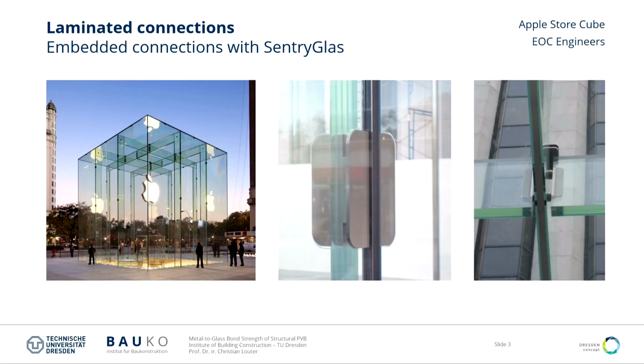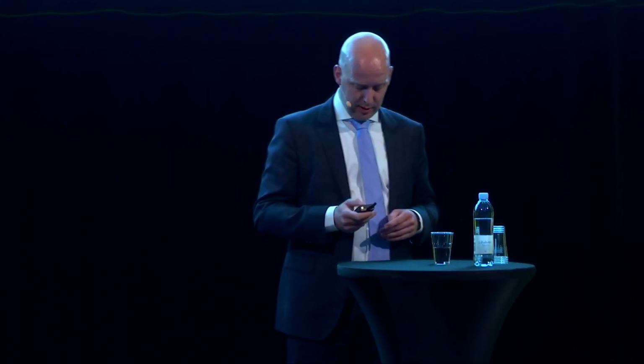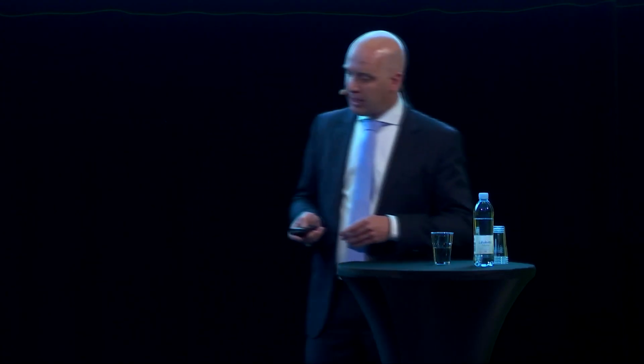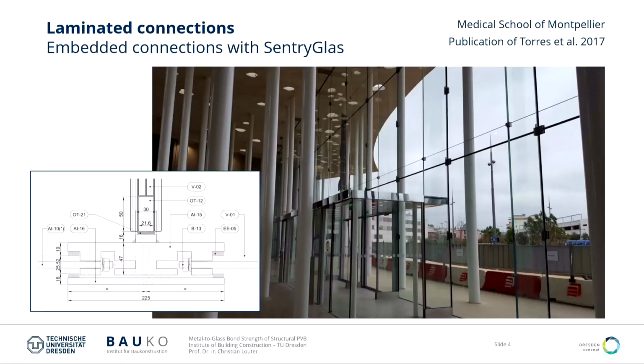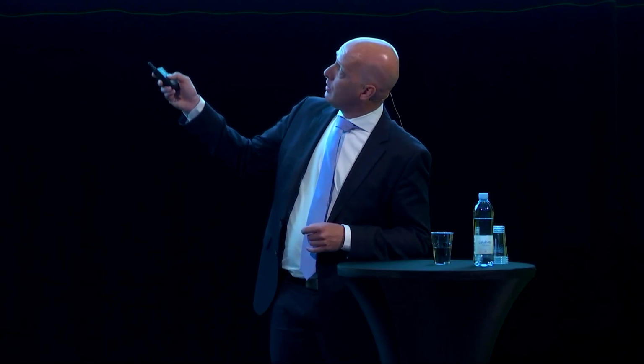In the Apple stores, there's quite a lot of lamination with embedded connections like here for the facade connections, but also embedded connections for the beam connections there. So this is then, for instance, laminated with SentryGlas. But you see them also in other projects appearing. Also here you see the connection between the glass facade and the glass fin. It's an embedded connection, as you can see here. 4 layers of glass, and this metal piece is laminated in between there.